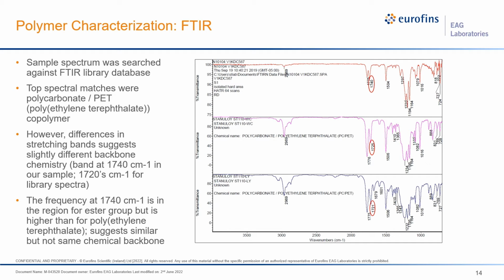The top one is of the actual isolated hard part of this medical device. And then we have some spectral library matches for a polycarbonate PET copolymer. And comparing the spectra, we can see that there's a lot of spectral overlap and similarities between them. However, if we zone in and look at this peak that's at about 1740 in our sample, it doesn't quite match up to the peak in our reference spectra that's at about 1720. This corresponds to an ester-type functional group that's on the polymer backbone. So this may suggest that the material is some sort of a polycarbonate polyester mixture, but it may not actually be PET.